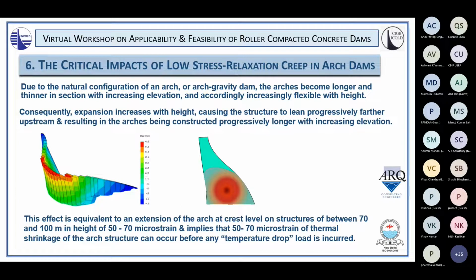And this effect is equivalent to an extension of the arch at the crest level, on structures of between 70 and 100 meters in height, of the order of 50 to 70 microstrain, which implies that 50 to 70 microstrain of thermal shrinkage can actually happen in that arch crest before it effectively experiences any temperature drop load.